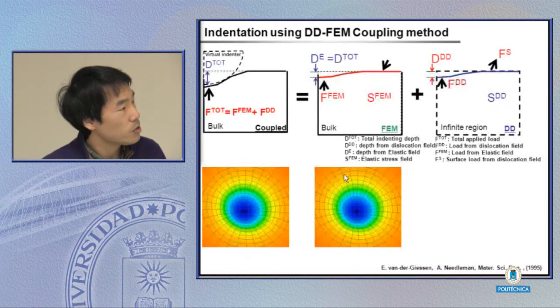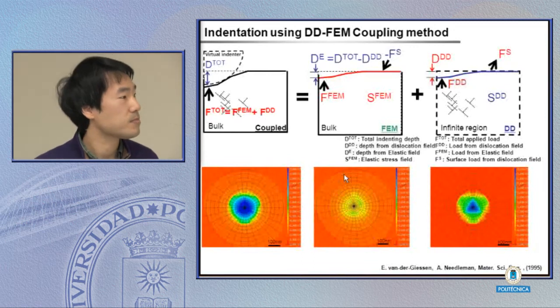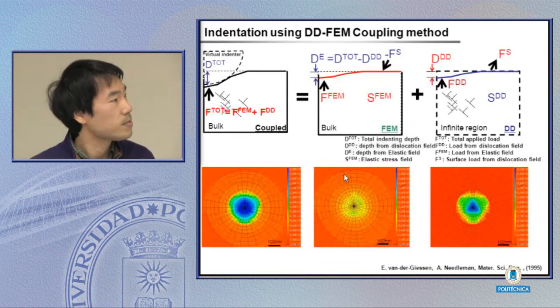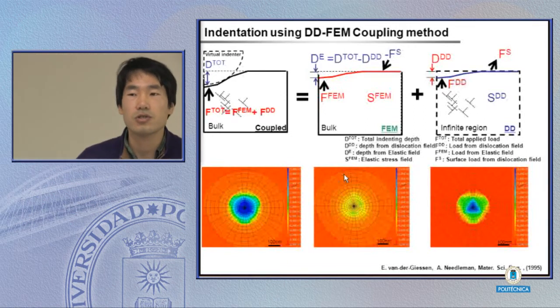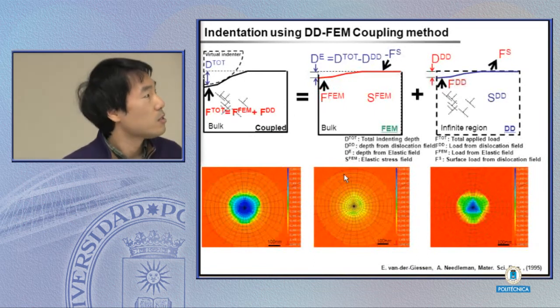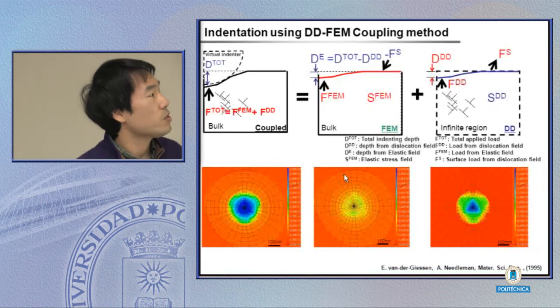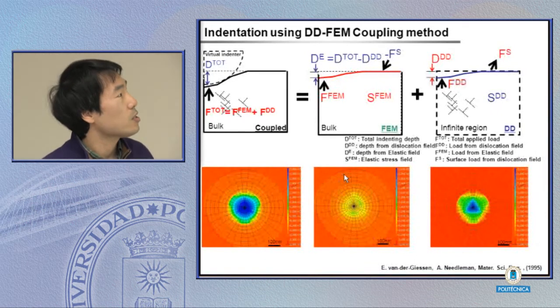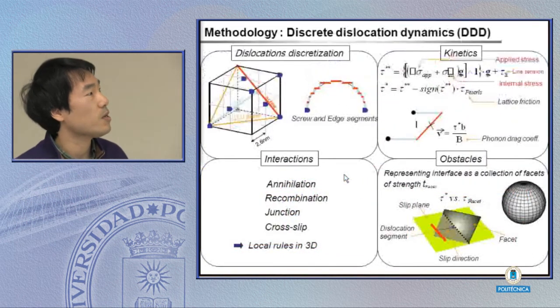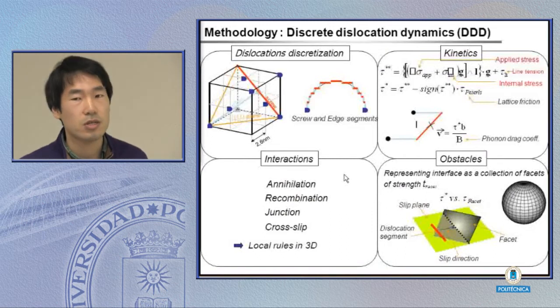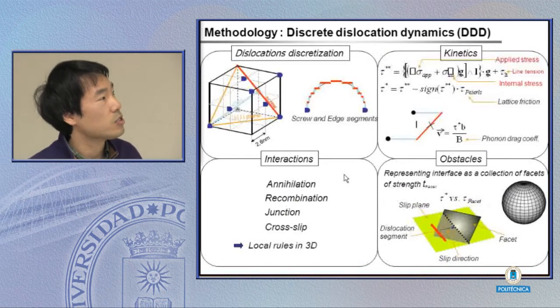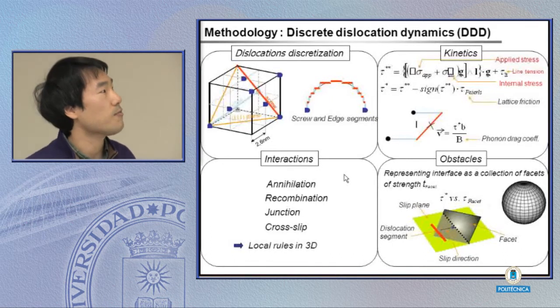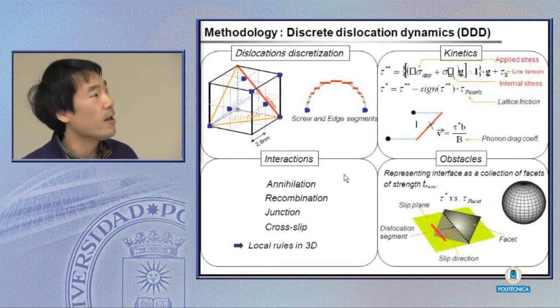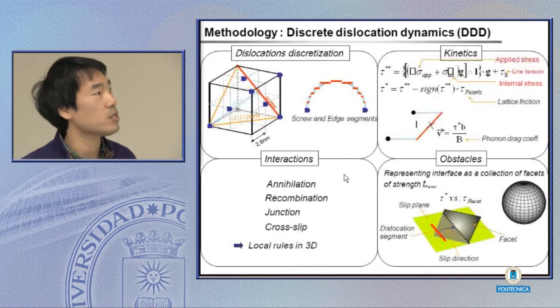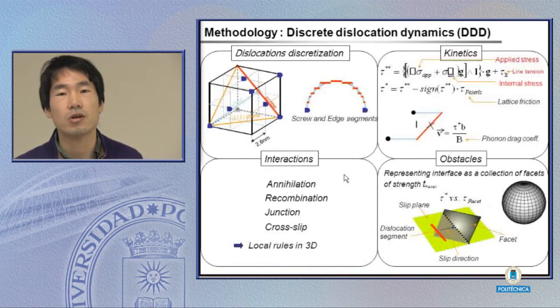For this kind of simulation, we do these hardening parameters. And we do an indentation test using the dislocation dynamics too. At the beginning of the dislocation dynamics, we don't have the dislocation inside the bulk. So at the beginning, the simulation result is totally the same as the FEM calculation. However, as soon as there is some dislocation inside the bulk, the dislocation structure and the stress field due to the dislocation affect the final result. And this dislocation stress also affects the boundary condition of the FEM calculation.